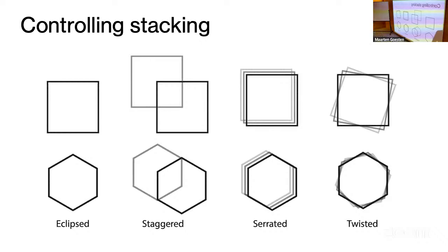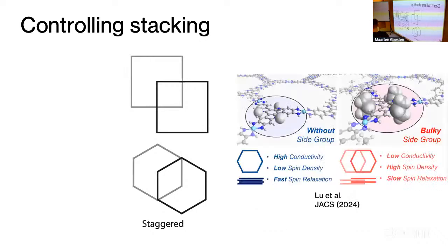Usually electron diffraction is the way to figure that out. But if, for instance, we would lose the 6-fold rotational axis in the Kagome lattice, then you can forget about your crossing at K and at H. So it's very important to control it. People are doing a lot of work on that.